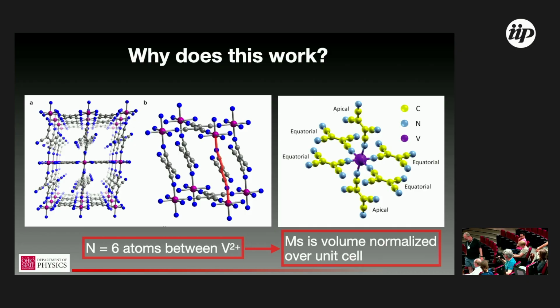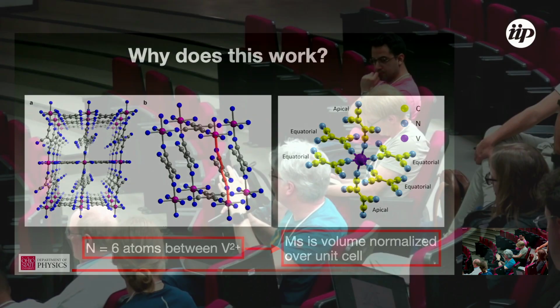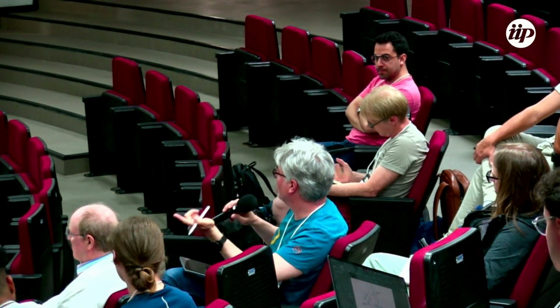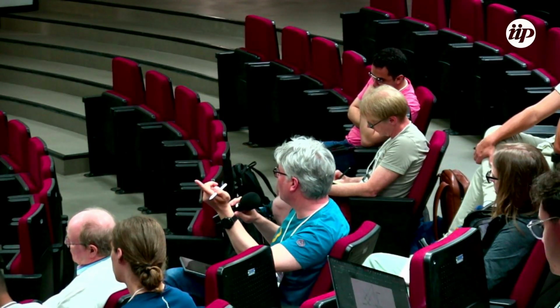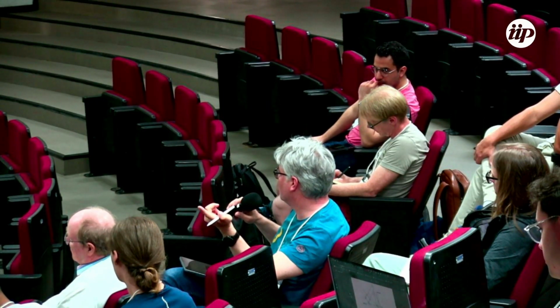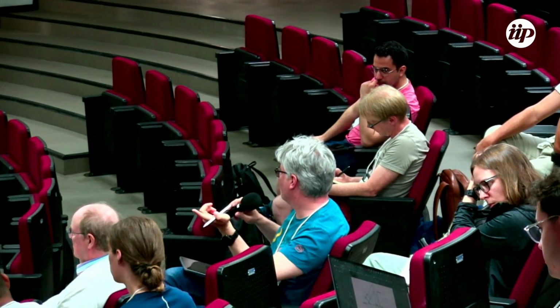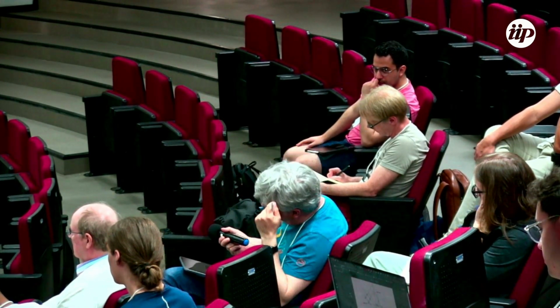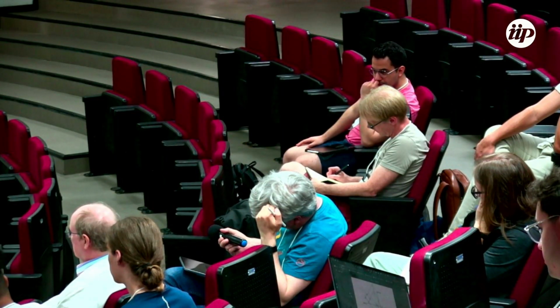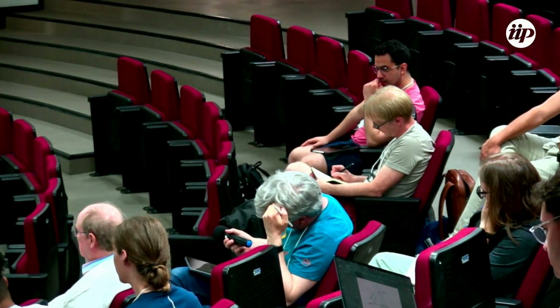No, I have a question related to that. So if I follow up on your trajectory, would you say that I should expect a highly anisotropic damping, depending on the magnetization orientation, how I prepare it in this crystal? And isn't it just the anisotropy? Yeah, so that disentangles depends on the spin-orbit interaction and how it plays. And in this situation, the only spin-orbit interaction is on the vanadium, which has a pretty highly symmetric coordination. There's essentially no spin-orbit interaction on the TCNE. So operationally, it seems like it's not anisotropic, and it probably wouldn't be anisotropic.